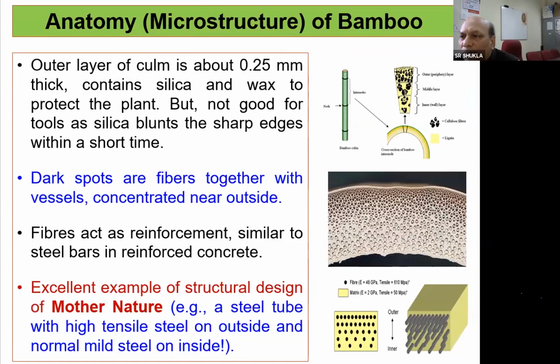This slide shows the internal structure of bamboo. Here we can see the bamboo is embedded with fibers, and these are the small black dots. These are the fibers, called vascular bundles. The skin of the bamboo is made of silica and wax, which is very strong and protects the bamboo from external damage. And the fibers you can see here vary in density from inside to outside. On the inner side, the number of fibers is less compared to the outside, where the number of fibers is more.